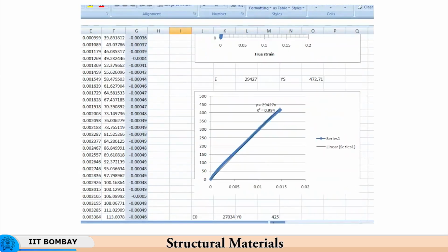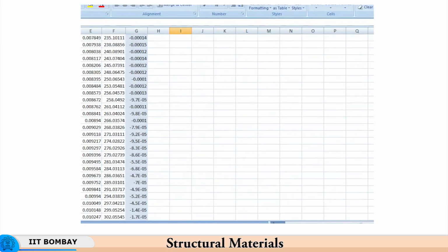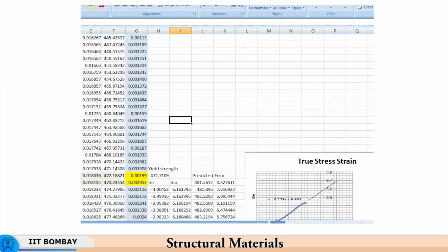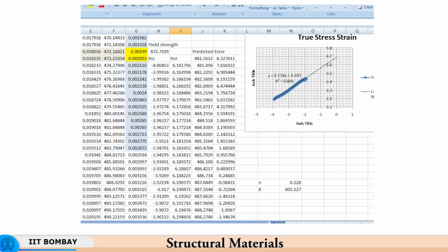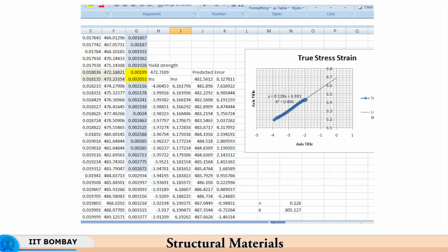So, when this parameter reaches the value of 0.002, then you call that the yield strength of the material. Now, you see that here it is 0.00199, so it is not 0.002, and here it is slightly over 0.002. So, you interpolate between these two values of stress, 472.18 and 473.23, to get the yield strength of 472.71 MPa.